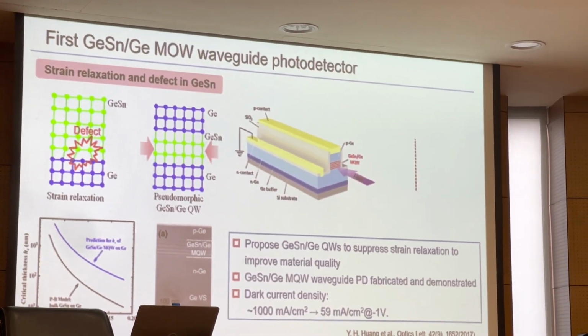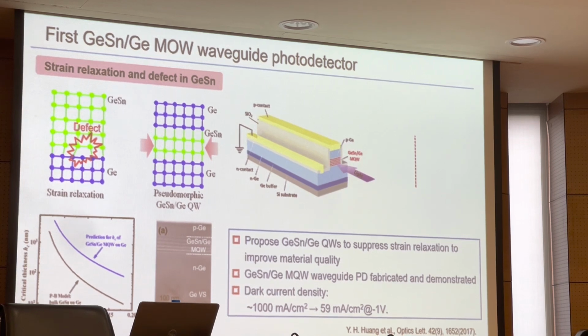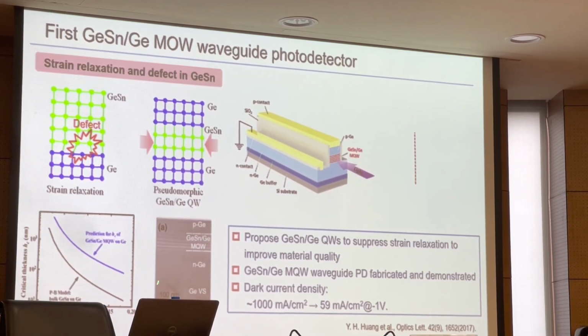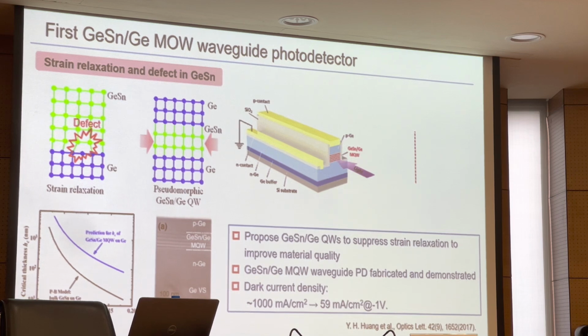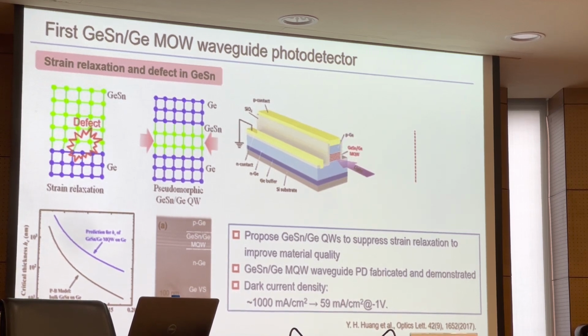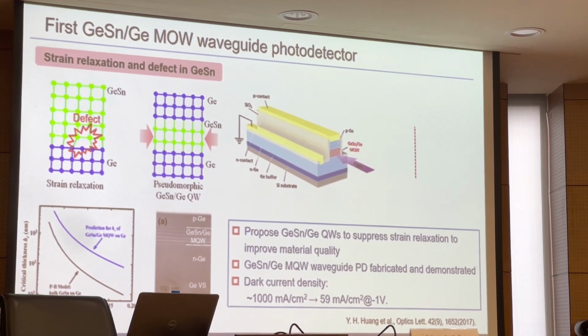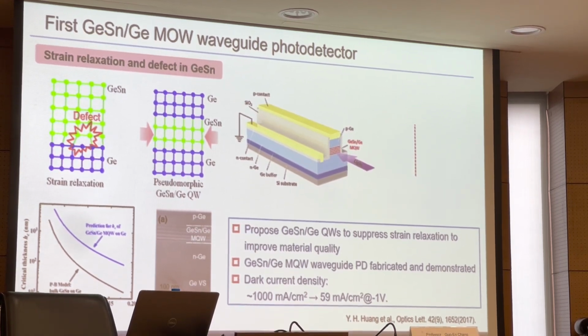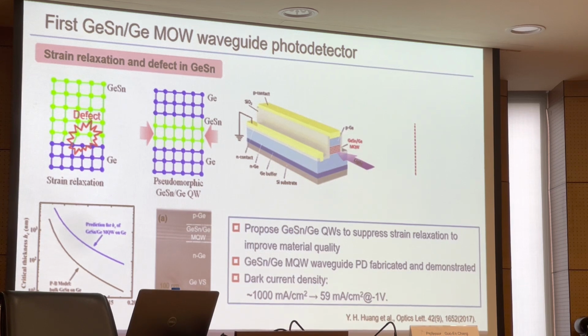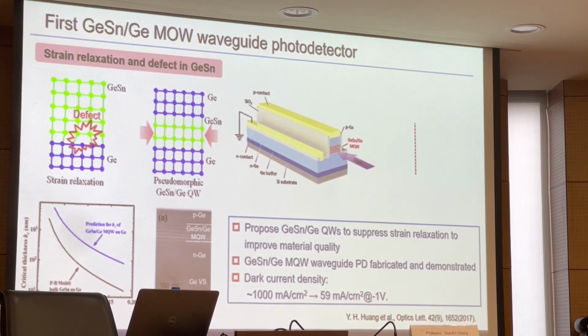So when the thickness is larger than the critical thickness, defects will generate and induce strain relaxation. This is one of the main sources for dark current, due to defect-related dark current.